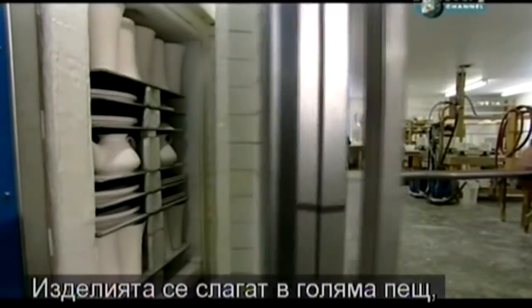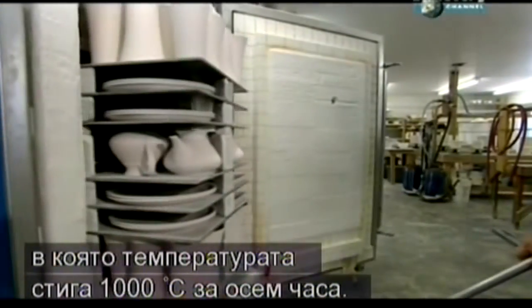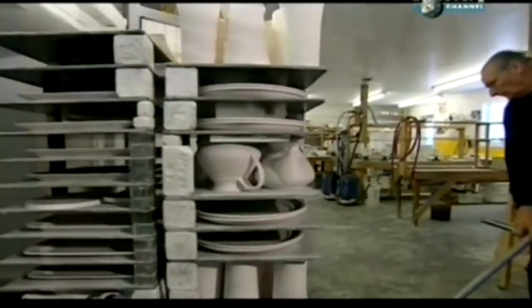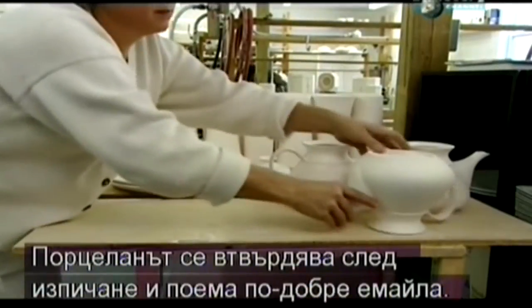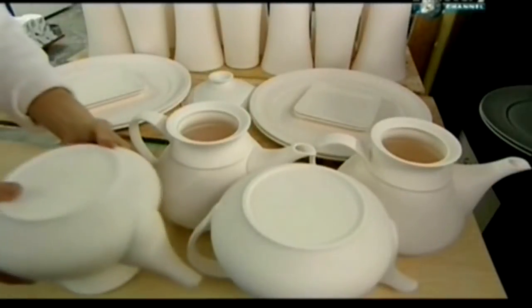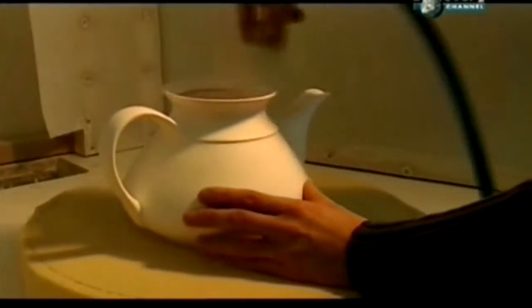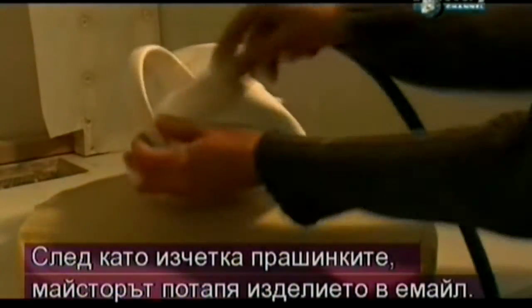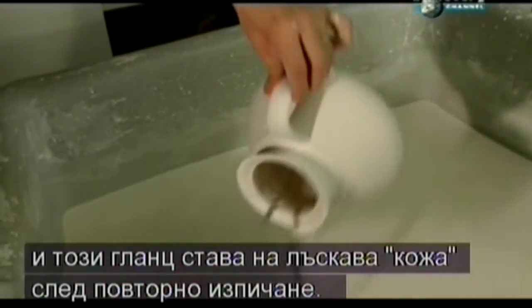The items are fed into a large kiln which heats up gradually, taking 8 hours to reach a searing 1000 degrees Celsius, and takes 12 more hours to cool down. Firing hardens the porcelain and enables it to better absorb a coat of enamel. After brushing off any dust, the craftsman dunks each piece in enamel, a protective coating. The porcelain absorbs it right away, and this glaze turns into a shiny skin once the pieces are fired again. Each piece is handled in a particular way to avoid leaving drip marks.